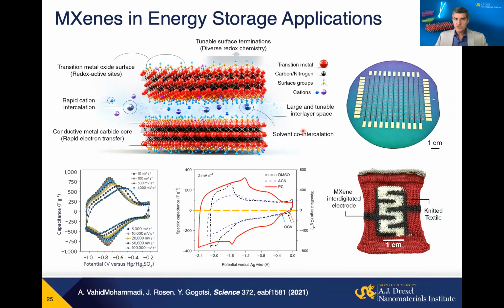Energy storage. My group has been traditionally working on supercapacitors, batteries, other applications. You can look at MXenes as a material that has electronic conductivity. It's basically highly conducting. So what it means, for example, is high power, high energy batteries. High power means you need to run a large current through your device. So you cannot do it using, for example, oxide cathodes in lithium-ion batteries. This material has the electronic conductivity needed, but there are also channels for ion transport between the layers. So it's possible to make materials which will have redox energy storage because of transition metal on the surface, which have very fast electron delivery and ion delivery, making ultra-fast energy storage devices. And again, they can be bulk devices, but they also can be printed on a silicon wafer, as you can see here, or knitted or woven into textiles.